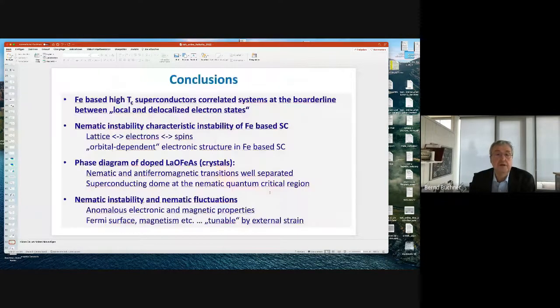in this weakly correlated system. So let me give you some conclusions, some take-home messages. The first take-home message which I would like to bring to you is that these iron-based systems are at the borderline between local and delocalized electron states. So electron correlations are relevant, less relevant than in cuprates, but they are clearly relevant in these systems. I've tried to introduce this nematic instability as a characteristic instability of these iron-based superconductors. I've argued it's clear that lattice, electrons and spins play a big role here. They are strongly coupled, and I've argued that orbital degrees of freedom play a crucial role here.